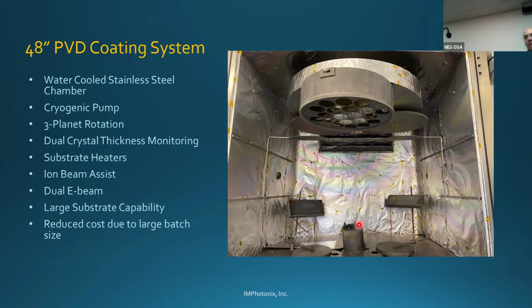So does that mean the sensors, do you have to clean them, or are they disposable? Disposable. I'll have to check with my CFO how much we pay, but I think it's like $2.30 per crystal, and we buy them by the thousands. Every run, you throw the crystal away and put another one in. You're always starting at about 6 megahertz, and the technician has to always make sure that the frequency is the same when they start.